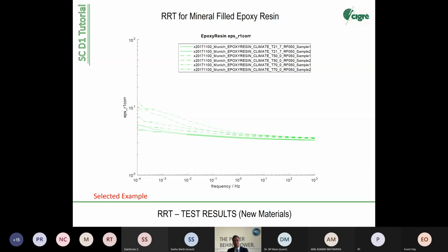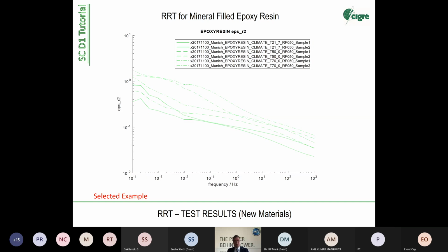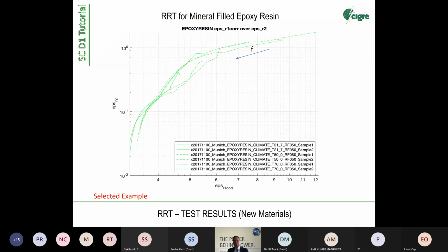Same applies for glass fiber reinforced materials. Same applies for all kinds of mineral filled materials. It's also lessons learned here. So the quality of materials can be checked with these methods in a very good way. Imaginary part also in a low range with a relative flat response compared to the others speaks for the same feature, good quality material. You see again the Arrhenius characteristic when the temperature is changed. But you still see a response. You still see the Maxwell-Wagner effect is active. Can also be confirmed here.